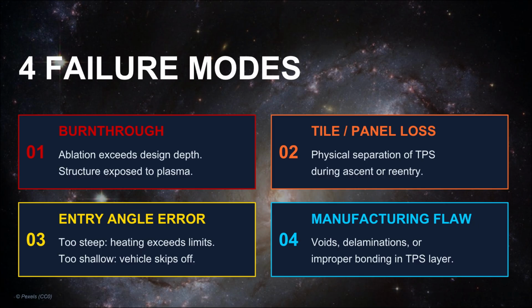Manufacturing defect: voids, delaminations, or improper bonding in the TPS layer. Columbia was tile loss combined with a damaged material type, RCC, that had no repair capability on orbit. Current crewed vehicles have on-orbit inspection procedures. Orion's heat shield is photographed before re-entry. Dragon is inspected robotically after docking.